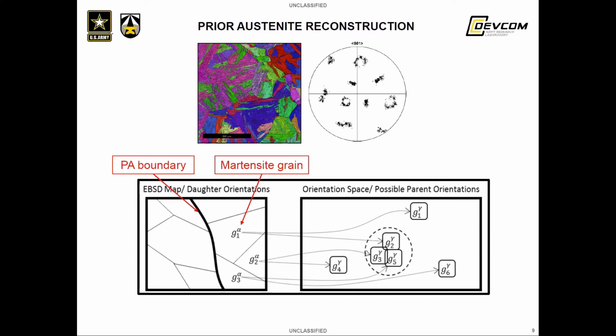The Kurdjumov-Sachs orientation relationship, while it defines the set of martensite orientations that you can get from a single austenite grain, the inverse of that relationship defines the set of possible parent orientations that could have given you a single martensite grain's orientation.